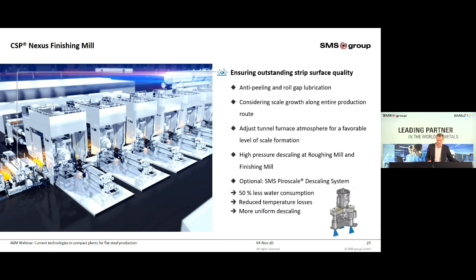State-of-the-art high-pressure descaling systems are positioned in front of both mill trains. Alternatively, the Piroscale system can be installed, which is a newly developed rotary descaling system. It reduces the water consumption by 50%, which reduces the temperature losses. The rotary system design leads to a more uniform descaling result.